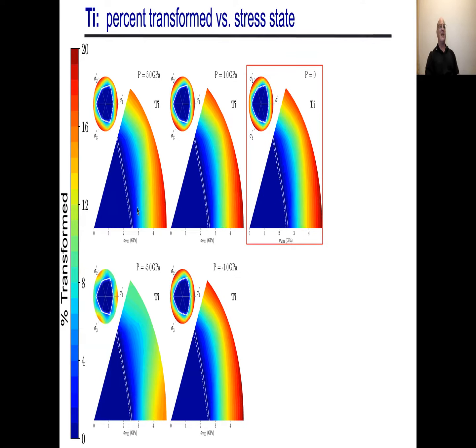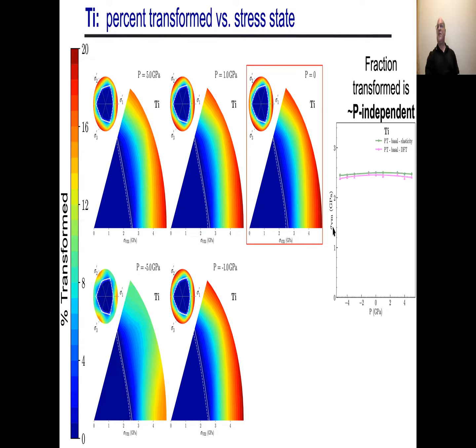I'm going to go back and compare this with the experiment in just a minute. Okay, here's titanium. Titanium is HCP to omega as you increase the pressure. And again, you see very little pressure dependence. This is P equals 0. And if I look at the transformation shear stress as a function of pressure, it's almost pressure independent. Okay. And again, DFT seems to work pretty well. Okay, let's go back and see how this does compared to the experiment where I have data.